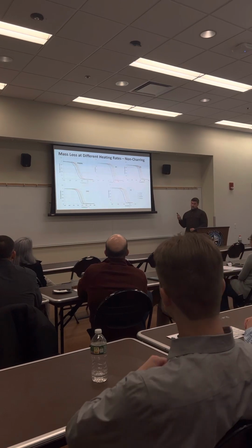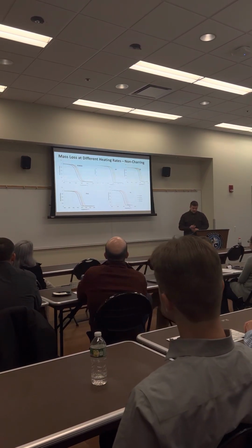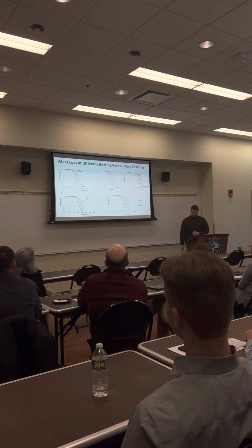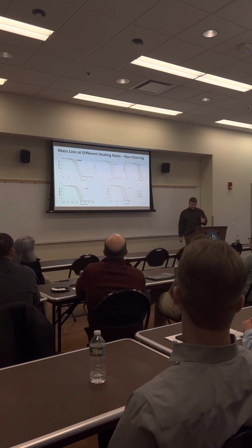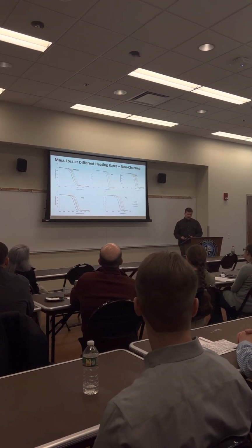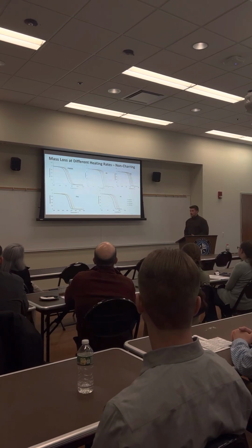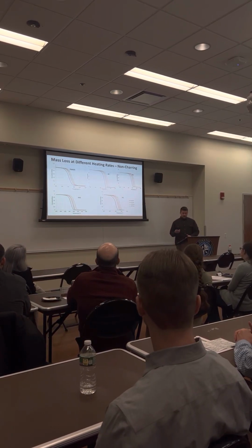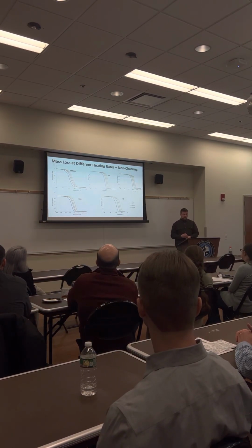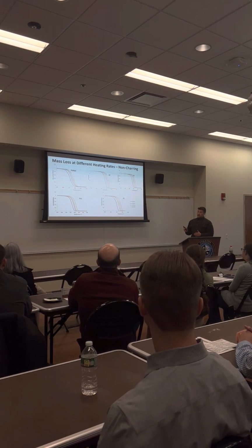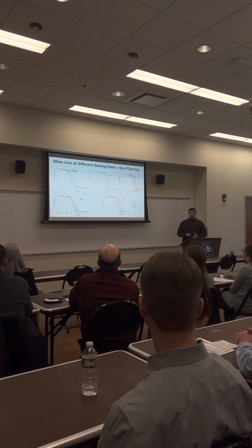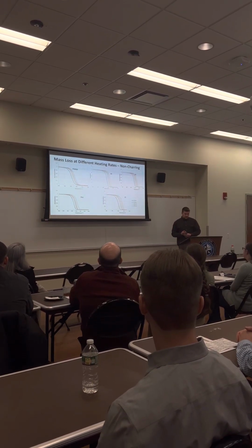If you take note of the right shift in the plots, the reason for the shift is that there's a more rapid rate of heating, which forces decomposition to reach a higher temperature, which essentially causes the degradation reaction to take place more quickly. That's true amongst all 9 of the samples. The next slide will have the charring species.